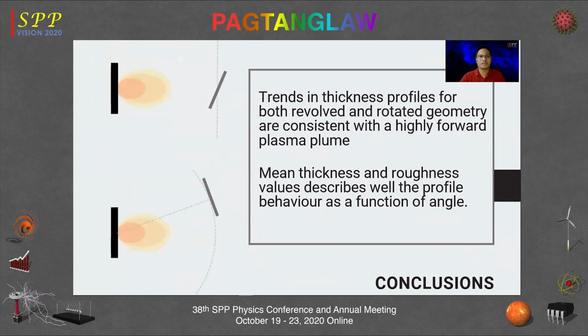In conclusion, the trends in thickness profiles for both revolved and rotated geometry are consistent with a highly forward plasma plume. And the mean thickness and roughness values describe well the profile behavior as a function of angle.